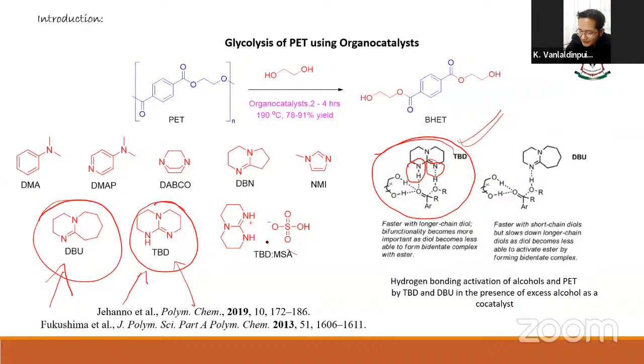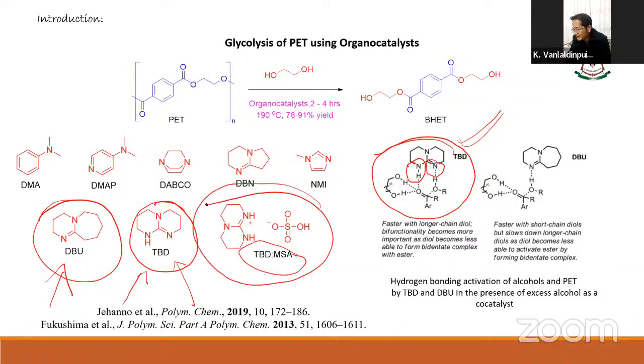And a mixture of TBD and methyl sulfonic acid is also used. Okay, as you can see here, the depolymerization process was completed in less than two hours when you use this mixture, giving 91% yield.